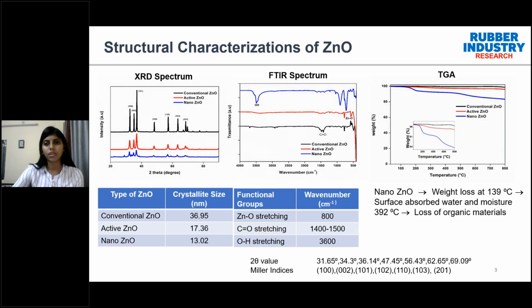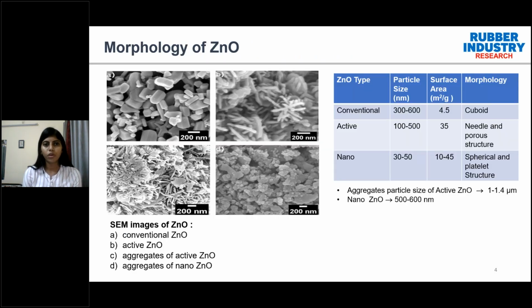When we look at the thermogravimetric analysis, that is, the degradation profile of the various zinc oxides, two prominent degradation profiles were observed for the nano zinc oxide. There is a weight loss at 139 degrees Celsius, which could be due to volatile materials or water absorbed on the surface, and another degradation around 392 degrees Celsius, which could be due to loss of organic materials present from the synthesis process of the nano zinc oxide. Coming to the morphology, conventional zinc oxide possesses a cuboid structure with a 300 to 600 nanometer size, and active zinc oxide has a needle and porous structure with a particle size of 100 to 500 nanometers. Finally, the nano zinc oxide has a spherical and platelet structure with a 30 to 50 nanometer particle size and an aggregate size of 500 to 600 nanometers.